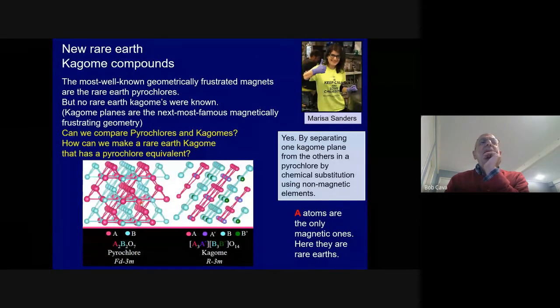So when you look at the crystal structure of where the metals are in a pyrochlore, you can, not so easily, see that you can separate the crystal structure into two sublattices. And they both have corner-sharing tetrahedra. And then the other realization is that you can take that same array of lattice points and distribute different kinds of atoms on them, in which case you can separate the magnetic lattice from the next plane of magnetic elements by putting non-magnetic elements in between. So now we can take this lattice type, this pyrochlore, and for certain circumstances only, put non-magnetic atoms on some of the lattice sites to make the material go directly from a pyrochlore to a Kagome net. So this red net is a Kagome layer.